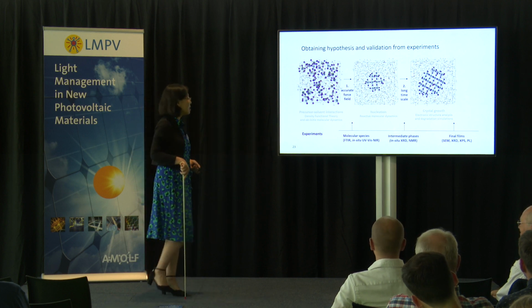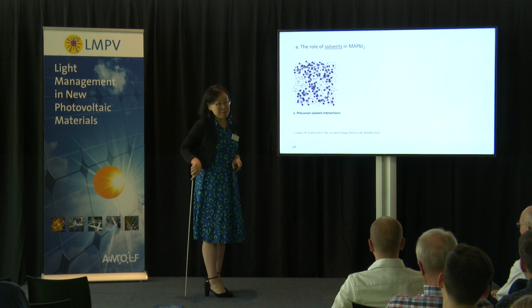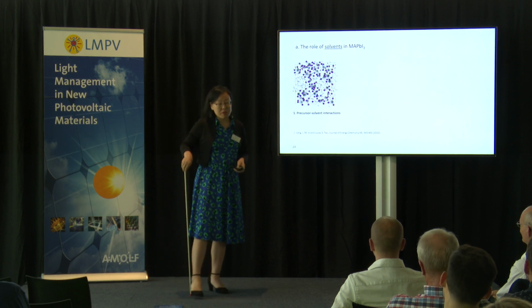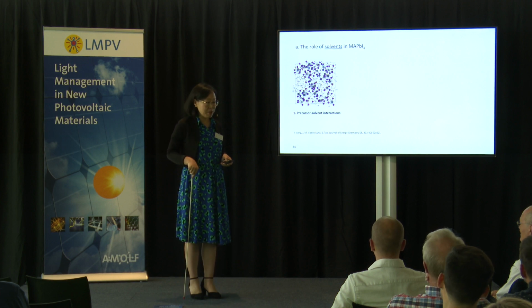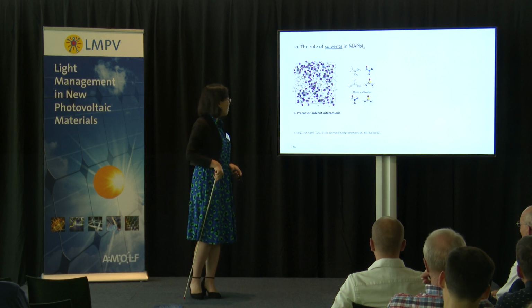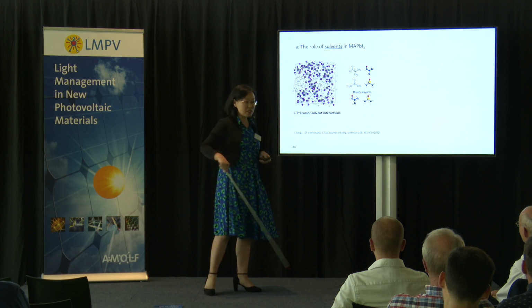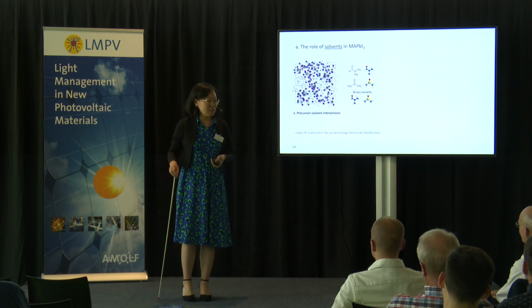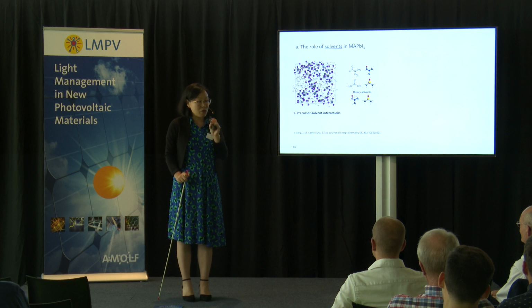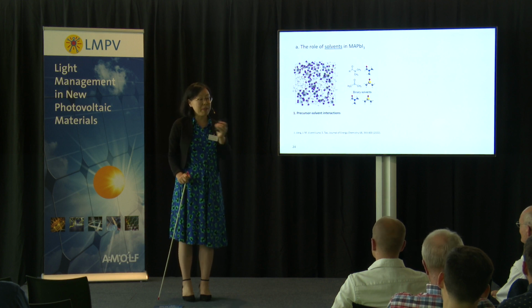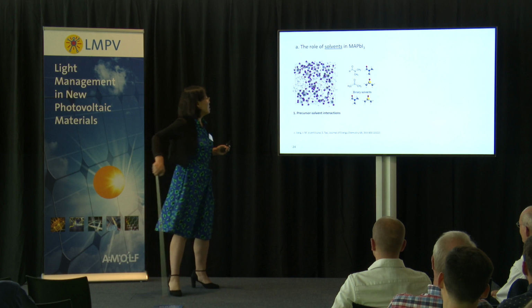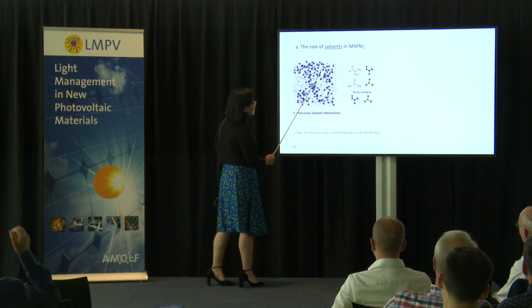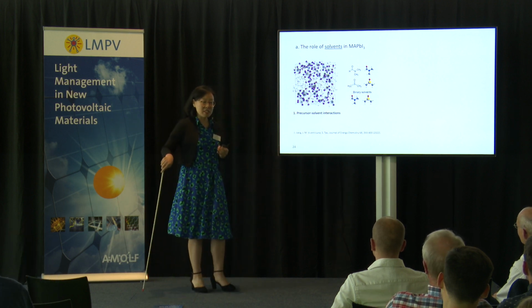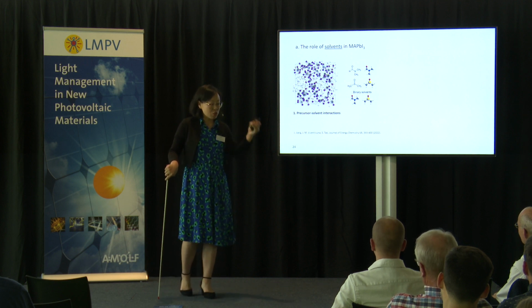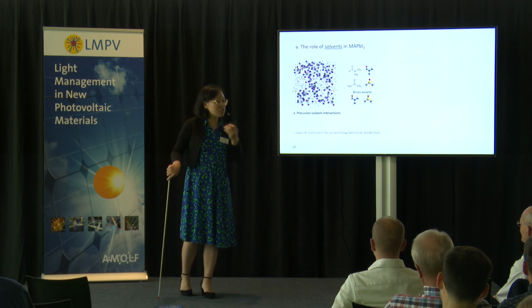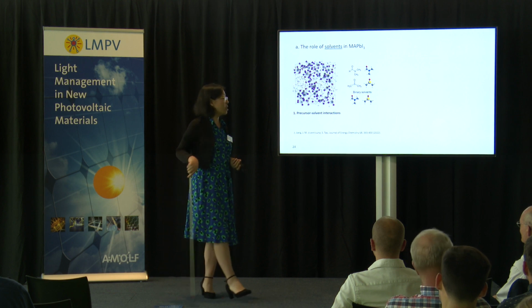But now I'll show you just some small examples of what we worked on. The first example is the role of solvents in the growth. Typically, we know that in the lab there are two very popular solvents, DMSO and DMF. They are added to make the film, and the ratio of them, how we add it, impacts the film formation, in a way that the solvents actually interact with the lead species in competition with the halide interaction. The stronger interaction the solvent has with lead, that means the slower growth, and the opposite is true as well.